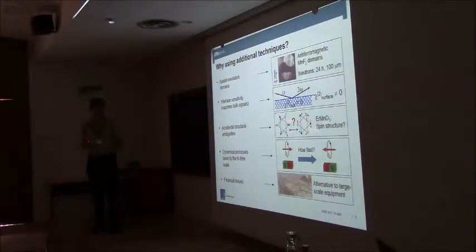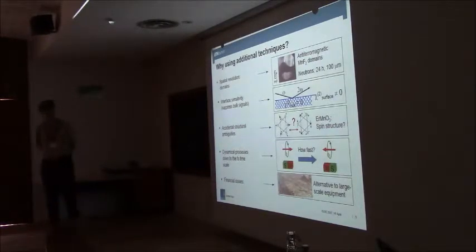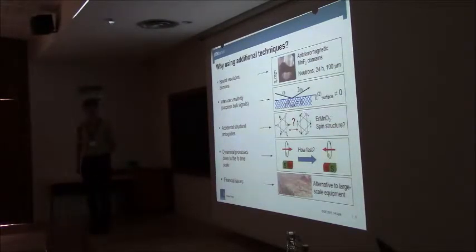Third, even a technique as powerful as neutron diffraction might have accidental degeneracies. For example, a spin structure like this, a triangular compensated structure like this and like that, are not distinguishable by neutron diffraction. You can calculate that, and if you have such a choice, you cannot really answer it. So you need something else to give this answer.